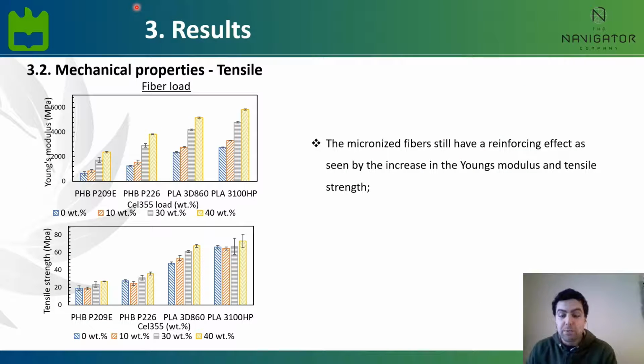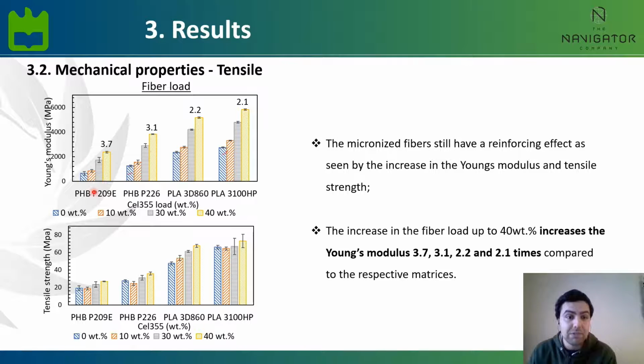So regarding the mechanical properties, and starting with the tensile ones, at first we can see that when increasing the fiber load of cellulose 355, we can also see an increase in the Young's modulus and in tensile strength. And that means that despite their reduced size, the micronized fibers still have a positive reinforcing effect. In fact, the incorporation of 40% cellulose 355 increased the Young's modulus by 3.7 and 3.1 times for the composites with PHB and 2.2 and 2.1 times for the composites with PLA in comparison with the matrices.